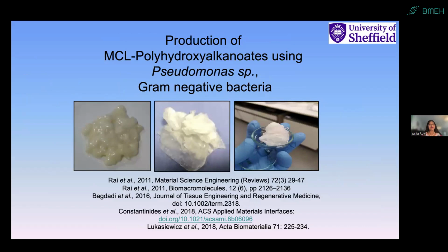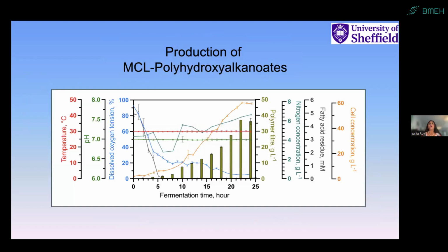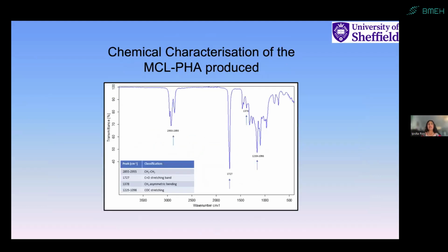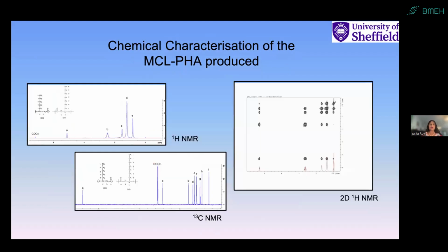However, for MCL PHA production, I have to use gram-negative bacteria because gram-positive bacteria do not produce MCL PHAs, and the main species I have used is the Pseudomonas species. I've produced many different types of medium chain length PHAs and again used controlled fermentation for the production. Here is the FTIR spectrum of the polymer. Here is the NMR, and in this case we also did a 2D NMR to ensure that the polymer we produce is absolutely the same as we desire to produce.